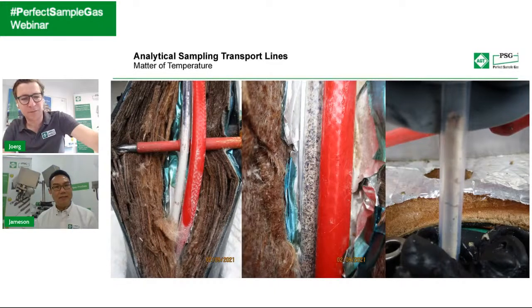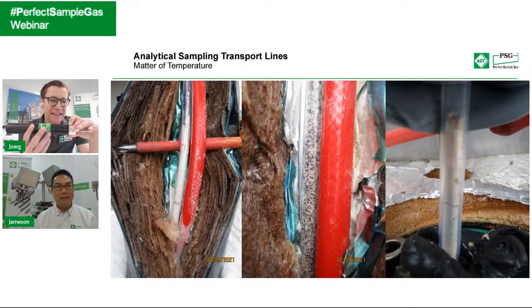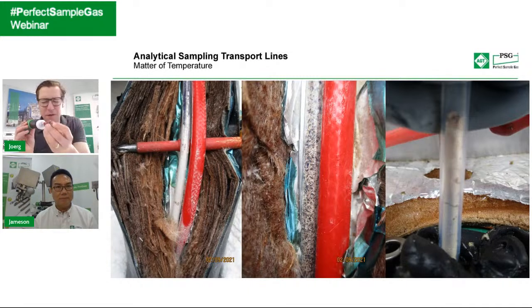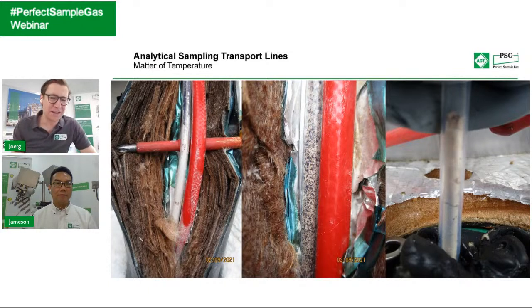Inside the components of a heated sample line, and sometimes that's maybe a little bit underestimated, the heated sample line represents the longest surface of all components in the sample handling system. So if you choose some bad material, or if this material, for example, shows some outgassing or some other effects, this will also affect your probe. Therefore, I think it's quite important to choose high quality products and to make sure that your heater is heated everywhere. Sometimes when you have a zone heater and you cut this at the wrong place, you will see some problems there because there might be a cold spot even in the line. Absolutely, yeah.